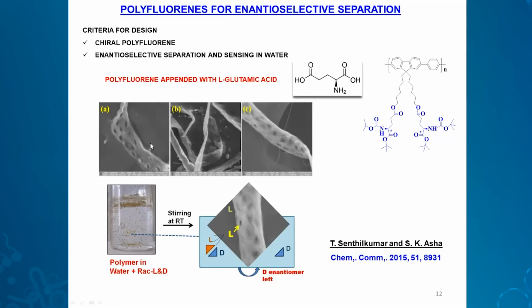And when these porous polymer powders were used for the enantiomeric separation in water, it is a mixture of D and L isomers, and into that the polymer powder is added and left to stir for 48 hours. And then you filter and remove this polymer. Then you evaluate the CD spectrum of the remaining water.